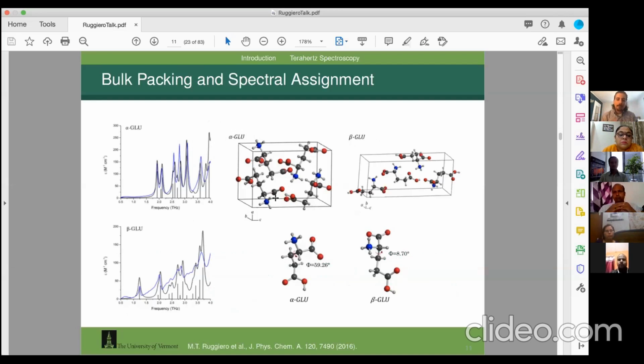One of the really powerful things about terahertz is it is extremely sensitive to very weak forces. And what that means is that if I have crystalline polymorphs or materials where it's the same kind of molecule, but they pack together slightly differently. And on this slide, what we have is glutamic acid, the basis for MSG. And the molecules are almost identical. There's a slight rotation of the dihedral angle right here and here. But you see, they both have carboxyl groups. They both have OH bonds.